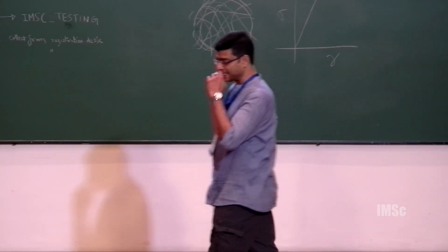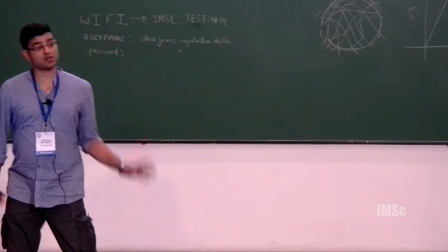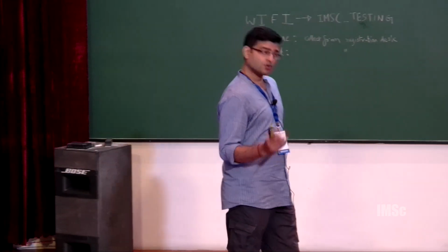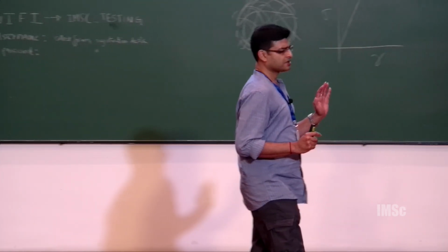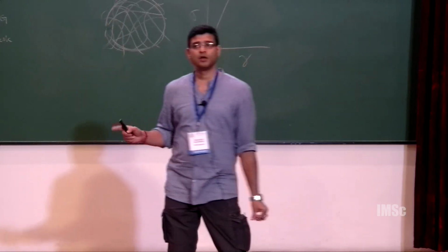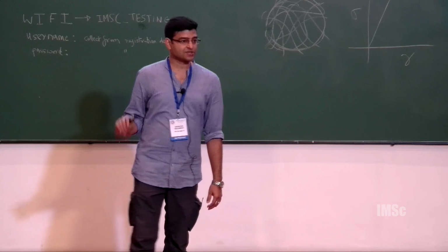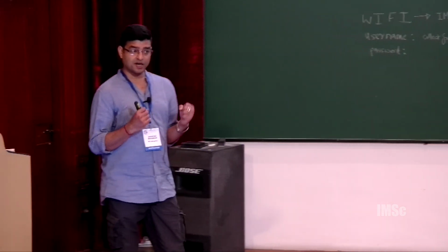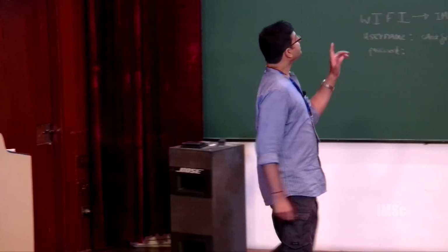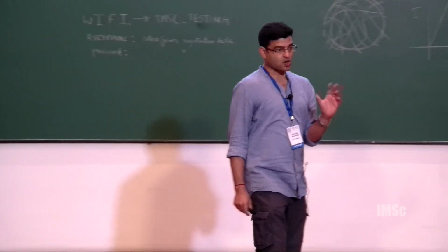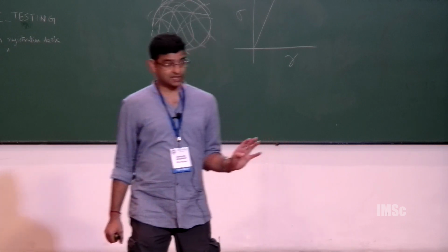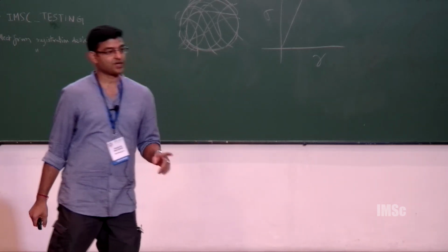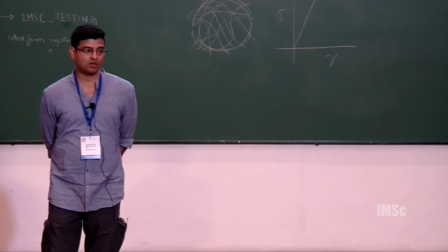Yeah, definitely. Because the relaxation is slow in this system, as they are a glassy system, and there is residual stress. We did an experiment under step strain to see the relaxation time: even after 10,000 seconds, there is still residual stress in the system. But that is not necessarily coming from the interaction between the particles. These particles have charge, they are charge stabilized, but if you put some salt in water or something, there is no change as such. So this is dynamic slowing down in glasses, not because of any long range interaction. That can actually play a role, but not in this case.